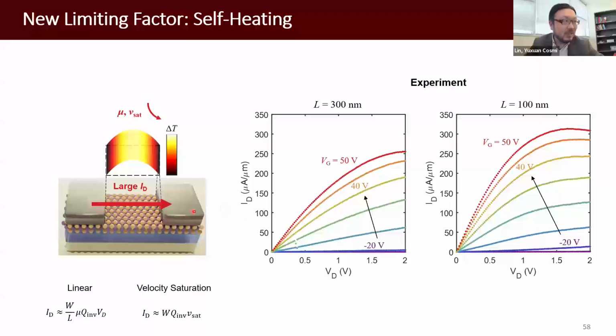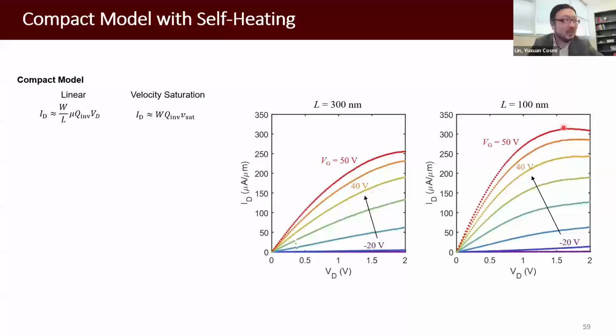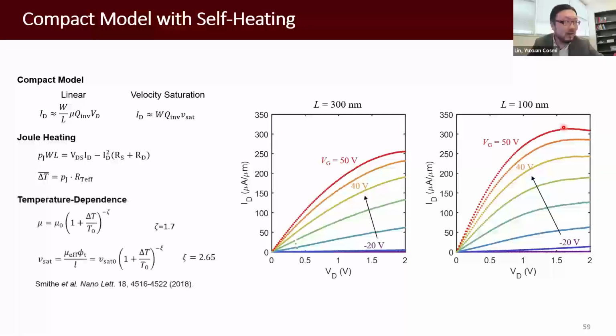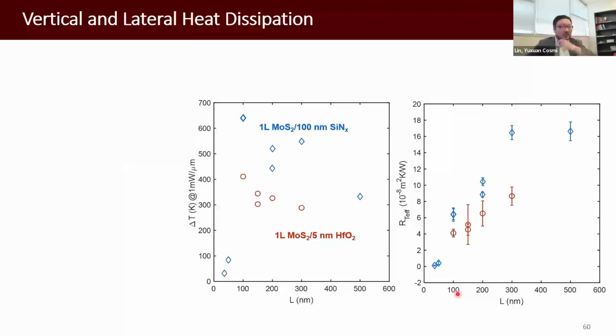When we drive a large current across the material, the middle of the channel is heated significantly. That gives you a degradation of the mobility and the velocity saturation. That gives you this drop of the current. We developed a compact model incorporating the self-heating effect, and we fit the compact model to this data. They agree reasonably well. But based on that, we can do further analysis.